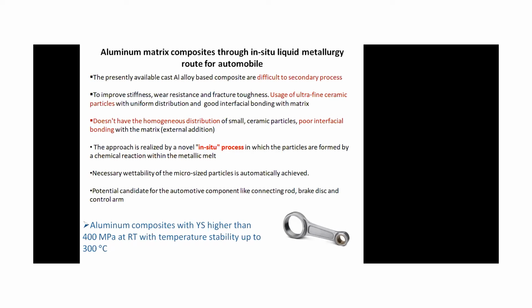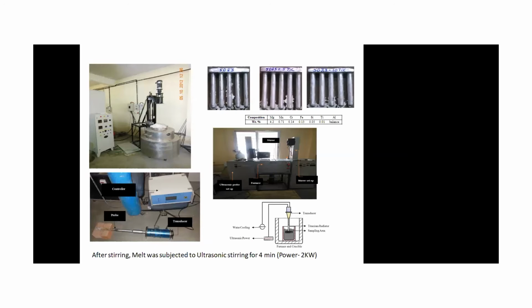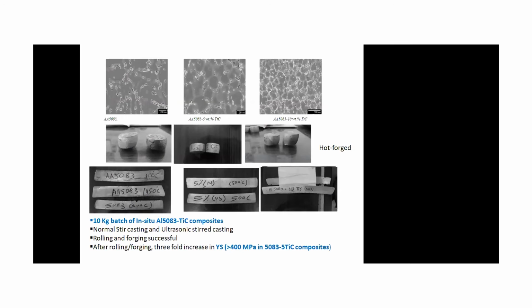So in order to increase the stiffness, wear property and other properties, it should have very fine particles, and also very high interfacial bonding with the matrix. That's why in the case of aluminum alloy, we have also added the TiC in the form of in situ reaction, and we can make components like connecting rods or brake discs and other things. And we have also rolled it. We have taken 5083 as the conventional alloy and we have made the composite. We have rolled it, we have hot forged it,